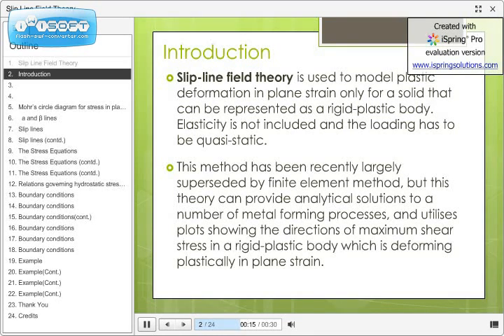This method has been recently largely superseded by finite element method. But this theory can provide analytical solutions to a number of metal forming processes and utilizes plots showing the directions of maximum shear stress in a rigid plastic body which is deforming plastically in plane strain.